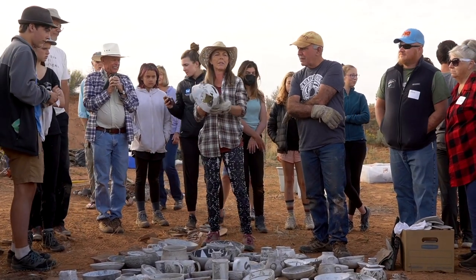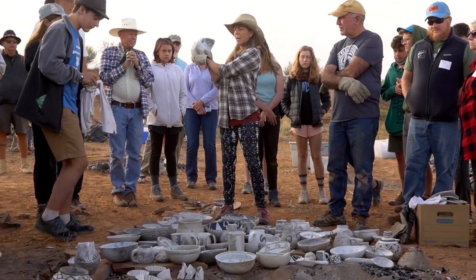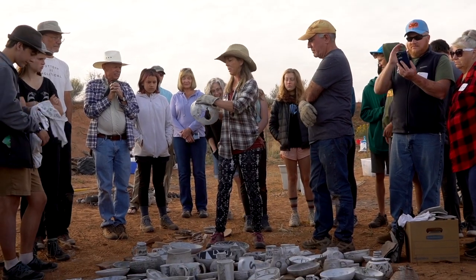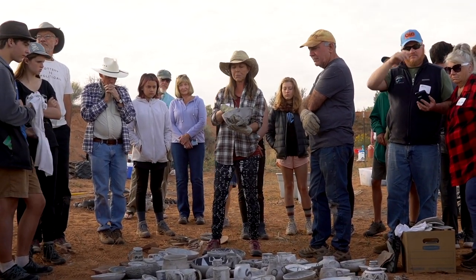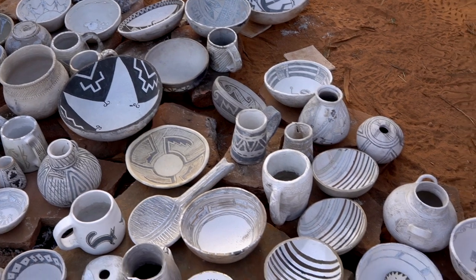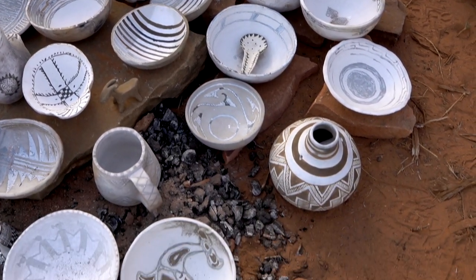It had its butt to the wind, probably maybe had a little moisture in it. I don't think this pot was totally dry. Sometimes we call this water spalling, but basically it's just snapping off, laminating off pieces. Would this pot have made it somewhere else in the kiln? It had moisture in the wall? No. But that's a water spalling. Then that's probably either too thick, which means it probably had water in it.